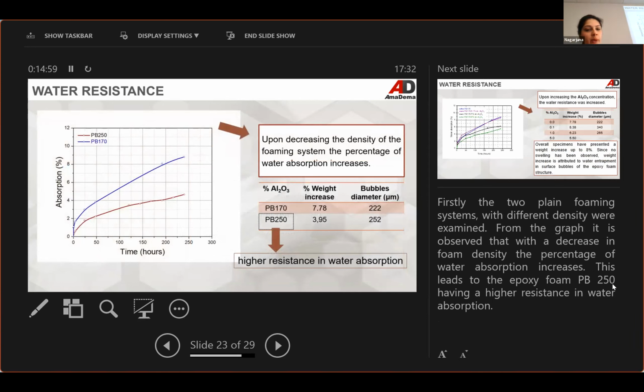What we have observed is that when we decrease the density of the foaming system, the percentage of water absorption increases. And these are the two systems we have investigated, with this system having the higher resistance in water absorption.